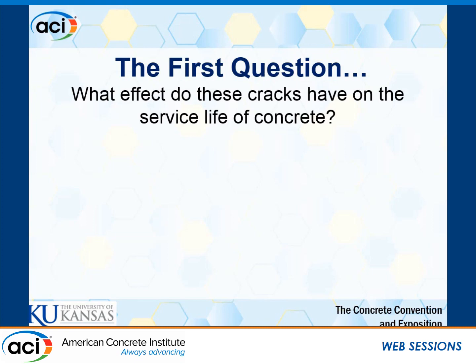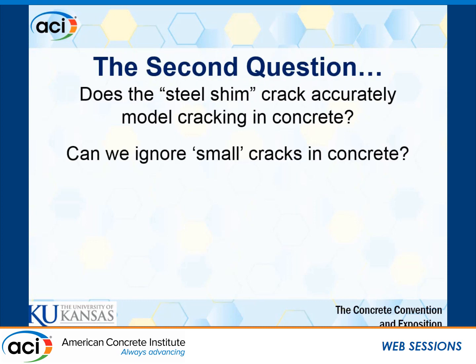The first question, whether we're looking at this from a corrosion or cracking standpoint, is what effects do these cracks have on the service life of concrete? And finally, getting a little bit more narrowed down to what we're looking at with this particular project: does this stainless steel shim really accurately model cracking in concrete?